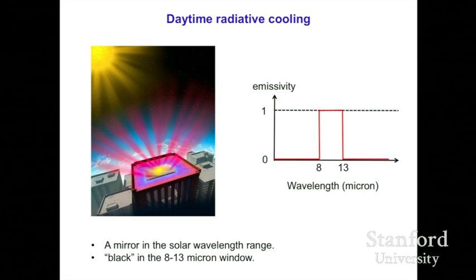So from this argument, you can quite imagine what you would do about achieving daytime radiative cooling. What you would like to do is to create a structure that looks like this, which has essentially zero emissivity in the visible wavelength range so that it doesn't get heated up by the sun. In the meantime, it would still be strongly emissive in the 8 to 13 micron window so that it can still emit the heat out. Now, remarkably, this is the kind of thing that is very difficult to find in nature. And therefore, it has been very difficult. There's never been any work that demonstrates this to the degree to allow you to achieve daytime radiative cooling.